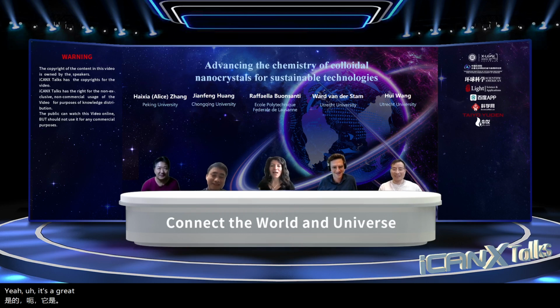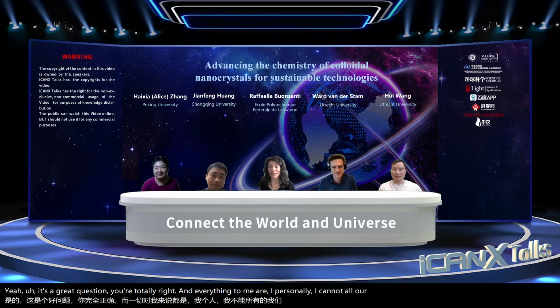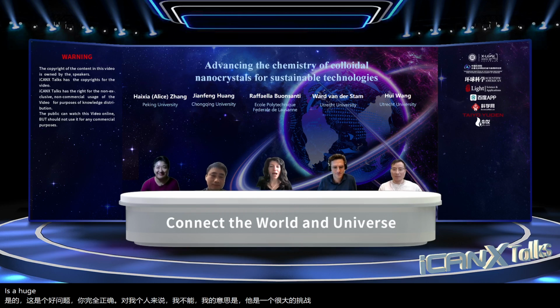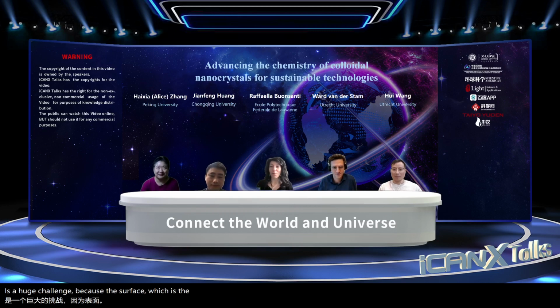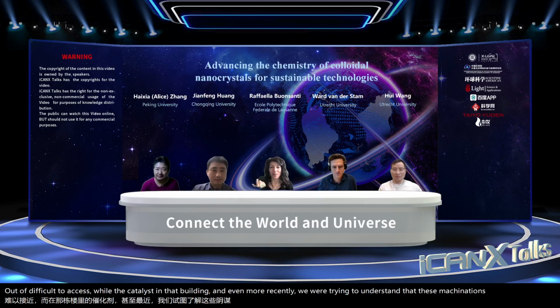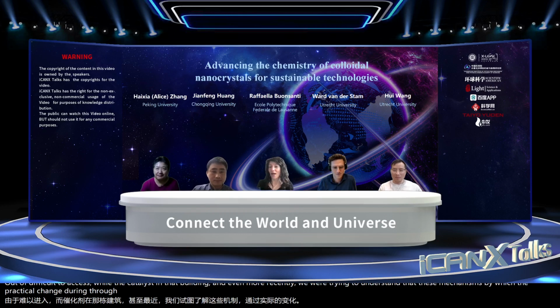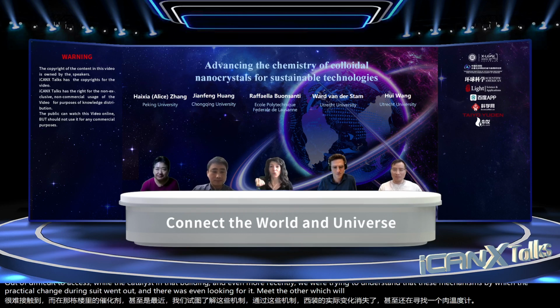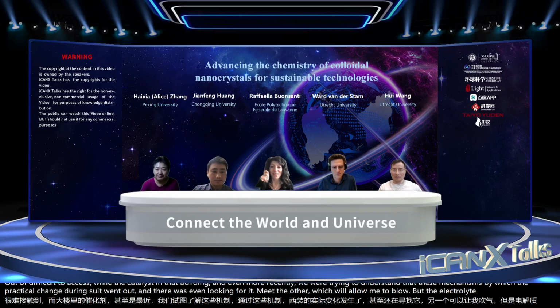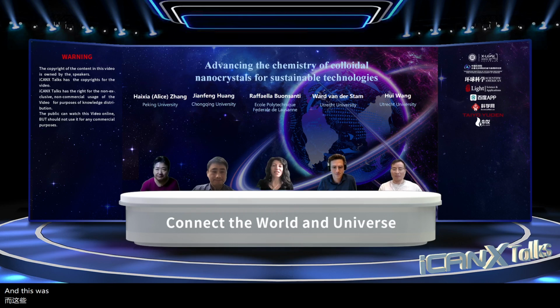Yeah, it's a great question. You're totally right. It's a huge challenge, because the surface and interfaces, which are the most important component which determine the catalytic activity, are difficult to access while the catalysis is happening. And even more recently, we were trying to understand better the mechanism by which the particles change during CO2RR, and I was even looking for a method which will allow me to probe the electrolyte in close vicinity of the metal. And this is even more challenging.